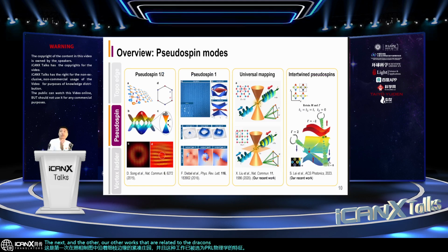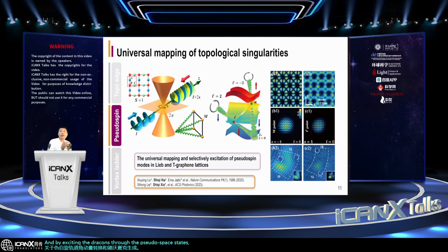The next of our works related to the Dirac cones is the universal topological singularity mapping from momentum space to real space. My main contribution in this direction is a universal mapping study on the Lieb and T-graphene lattices, which results in pseudo-spin orbital angular momentum conversion and vortex generation. And by exciting the Dirac cones through the pseudo-spin states, we provide the first evidence of the topology robustness during this mapping process.